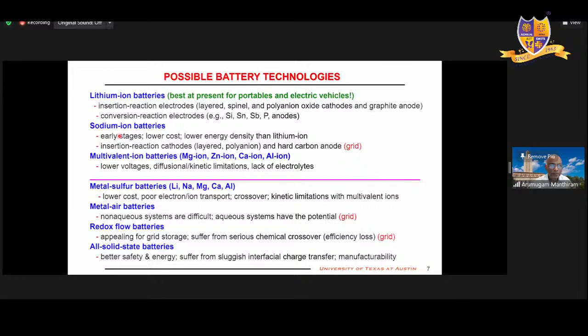So in the literature, what people do is throw a lot of liquid electrolyte so that you can overcome the poor ionic conductivity, and put a lot of carbon so that you can overcome the poor electronic conductivity. That is okay, but that will result in pathetically low energy density, because you put a lot of carbon that's not doing anything there, that junk sitting there, a lot of electrolyte, salt and solvent. That will all bring down the energy density pathetically to maybe 50 watt hour per kilogram, whereas right now it is 250 with the lithium ion. So it will decrease very much.